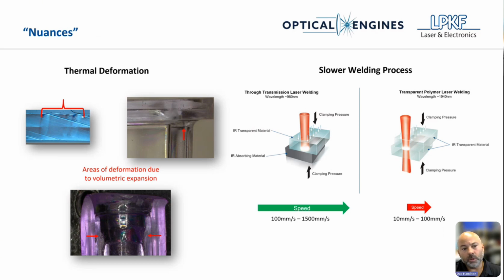Some of the nuances for 2-micron welding, I call them nuances. You can see them here in the picture. The top left picture is showing some of the volumetric absorption and somewhat thermal expansion there on the top. In the next one over to the right, you can see a little bit of a radius in this T-joint. That's obviously from deformation. This is actually a T-joint weld, and we're welding down from the top of this part. And on the bottom piece, you can see a half cutaway of a medical device fitting, and you can see the thermal expansion happening in the channels. We are welding from the outside in a radial format, and you can see this thermal expansion bubble starting to form on the inside of that part. There are ways around that. We'll get to that later in the presentation.